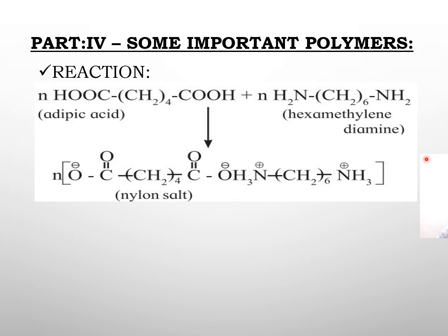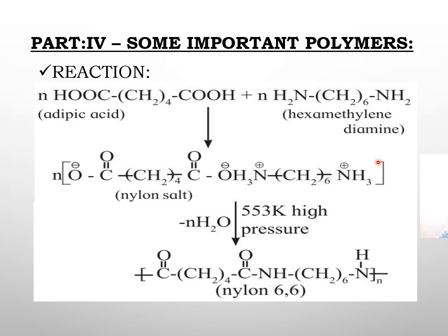Which on heating at 553 Kelvin under high pressure gives out water molecules and nylon 6,6 is formed. A water molecule is given out: OH from the adipic acid, H from the amine group, and a CONH amide linkage is created. When n molecules condense together, they form n molecules of nylon 6,6.